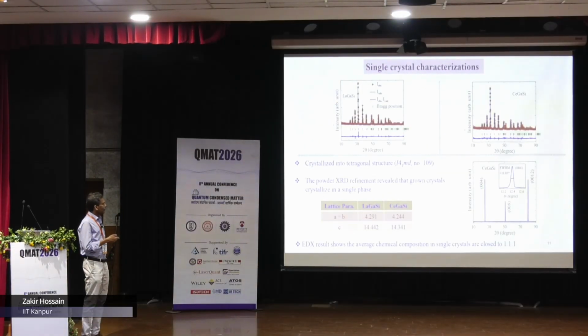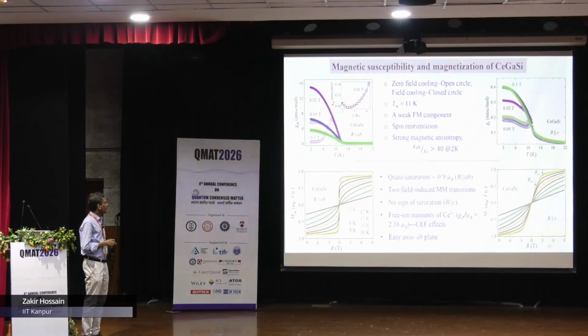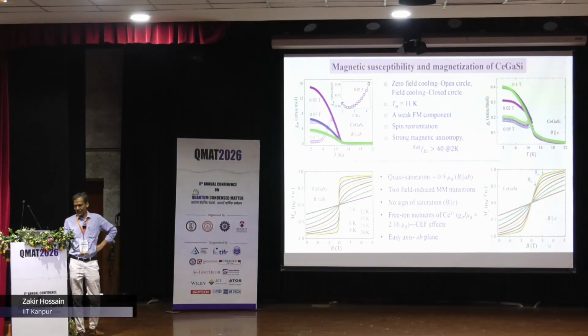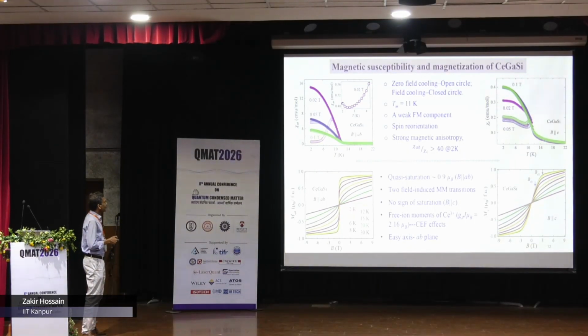So we did X-ray composition, everything looks quite good. And now comes the magnetic data. So let's see here. This is because we have the plate-like crystal. The c-axis is perpendicular to the plate direction, so one can apply magnetic field in plane, parallel to the plane of the crystal, or perpendicular to the plane of the crystal.